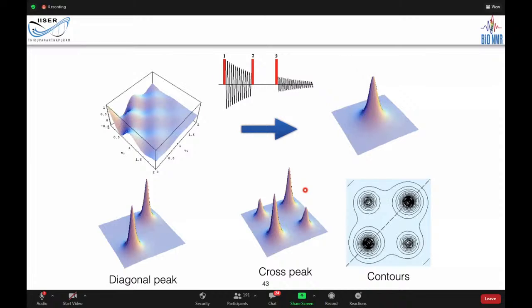Now normally we don't represent it like that. We represent it as contours like this. So you have a diagonal peak like this, and there is a contour peak in this direction. So what does this mean? This means that the spins corresponding to this peak and the spins corresponding to this peak are coupled to each other. Okay, so you get a cross peak if there is a coupling. It can be any coupling. It can be any magnetization exchange. Couplings can exchange magnetization. Chemical exchange can exchange magnetization. Okay, so all this is possible.